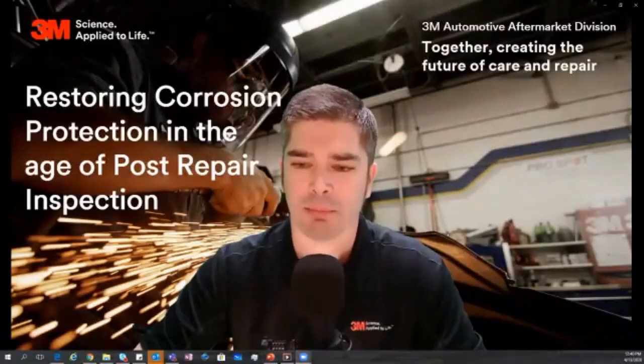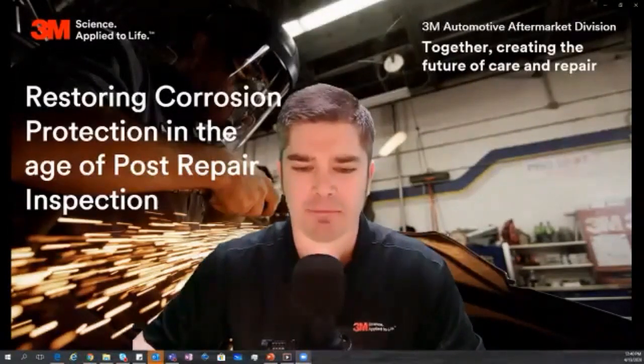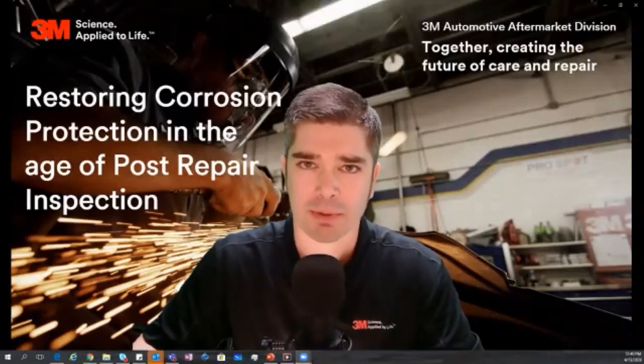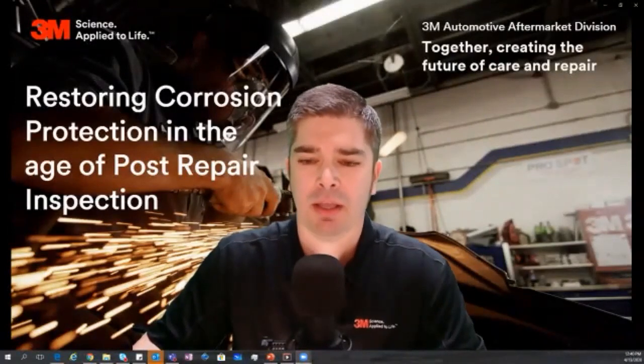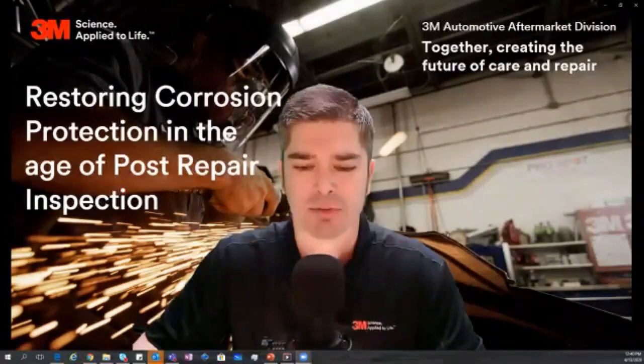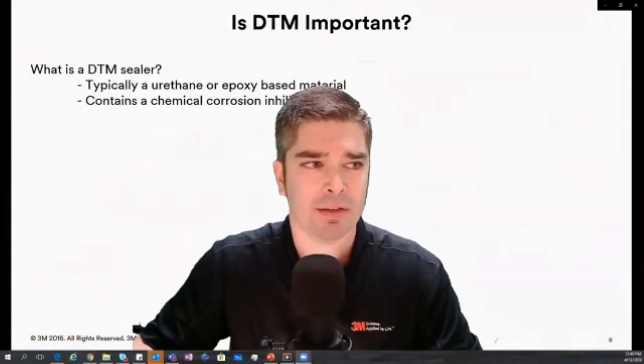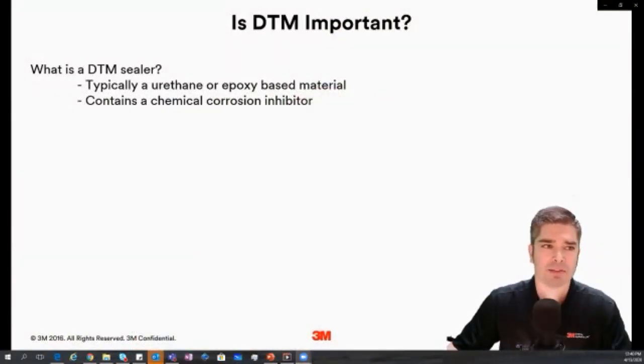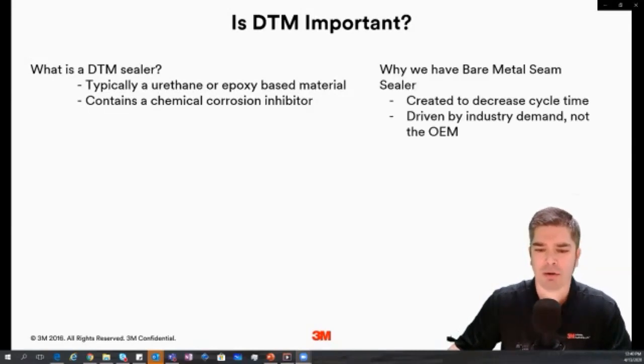This one comes up quite a bit, and what we really need to understand first and foremost is, what is a bare metal seam sealer and why do we have it? One of the things that we want to be certain of here is that we're using a seam sealer that's actually designed to be bare metal. It's going to have a chemical corrosion inhibitor built into the product, right? These are typically a urethane or epoxy base. But what's most important to point out is that these seam sealers exist in our industry today to try and decrease cycle times, right?